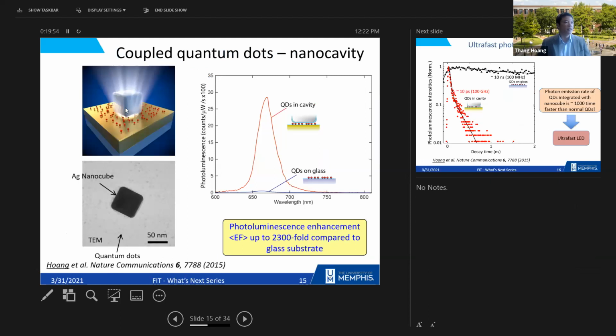What you see here is a schematic of the sample that we made. We have a gold film and we put the nanocube, and in the gap in between we put the quantum dot. And what happens is that the quantum dot underneath the cube is going to act differently than the other quantum dots that are not underneath the nanocube. At the bottom here you can see an actual sample that we made. We have a nanocube and the quantum dots show up as the dark dots. The nanocube itself has a size of about 75 nanometers, and the quantum dot has a size of about 5 to 6 nanometers, like I said before.